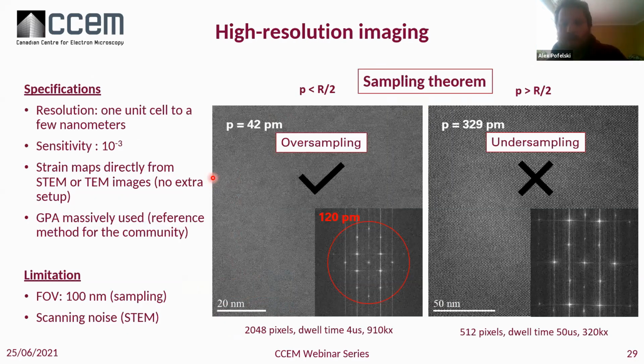So that will conclude this high resolution imaging. Usually the type of resolution that you have is 1 unit cell to a few nanometers. You can target a sensitivity up to 10 to the -3, which is already relatively good. The strain maps come directly from the STEM or the TEM images. There's no extra setup, you just have to follow this. And the GPA is massively used by the community and even used as a reference method. So when you develop a new strain mapping method, you usually compare to the GPA method to show its proof.